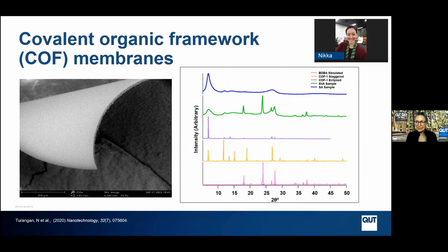That 10-layer thickness is actually an intermediate place where it's a bit tricky to use some of our surface science tools to investigate the materials, and we did a lot better when we moved to thicker films. So Nick has actually been working on this now for a while, and what she's come up with is a really nice approach to creating self-supporting COF membranes, and these only contain the 1,4-benzene diboronic acid. There are no additional molecular binders in there.